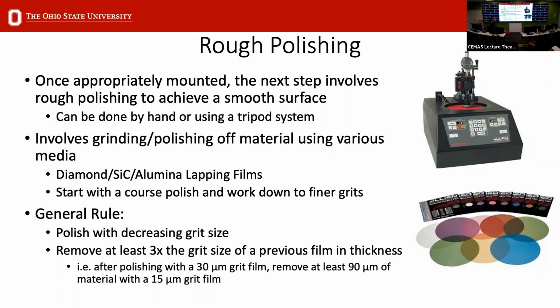A general rule that we typically use for polishing samples is, as you polish, you're changing grit size, and you want to remove at least 3 times the grit size of the previous film on your current film. So if you polish with a 30 micron grit film, when you move to the 15 micron film, you want to remove at least 90 microns of material with that 15. When you move to something like the 9, you want to remove 45 microns. That's just a general rule of thumb, to make sure that you're removing those damage layers, which, if you don't remove them, could hinder some of the analysis that I'll talk about a little bit later.